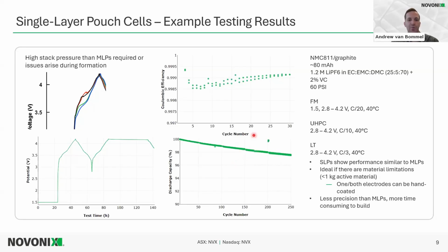The reason why one would use single layer pouches instead of a multi-layer pouch, one of the big reasons, is if our customer cannot provide enough active material for a full mix and coating run. So in that case, if they cannot provide enough cathode material, for example, we can hand coat that cathode material, match it with a machine coated anode single-sided, and then make single layer pouches. So again, just to summarize, these single layer pouches have less precision than multi-layer pouches, and they're a bit more time consuming to build, but if needed, we can make them.